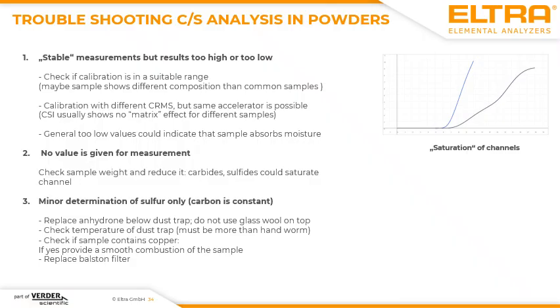When you only have a minor determination of sulfur, please consider, I would say, the unwanted effects I mentioned before. It could mean that you have an absorption due to moisture. And this does mean please replace the anhydrone tube below the dust trap because then it is worn, you have moisture inside, which again absorbs the SO2. Also check the temperature of the dust trap because it could mean when the dust trap is no longer working reliably, you also have a condensation of water here, which again absorbs SO2.